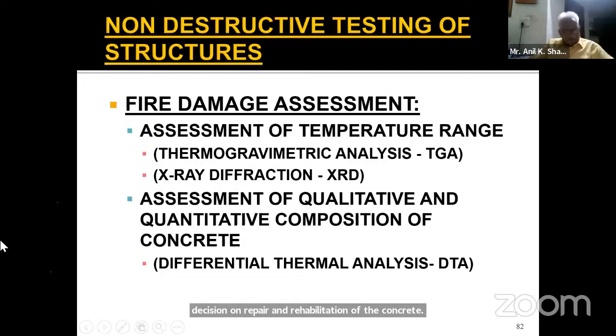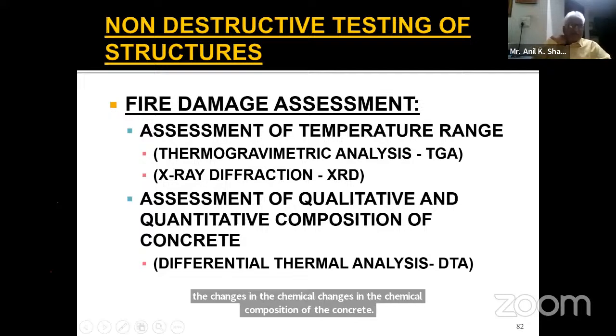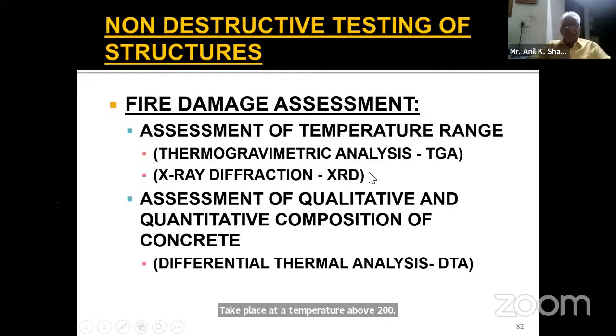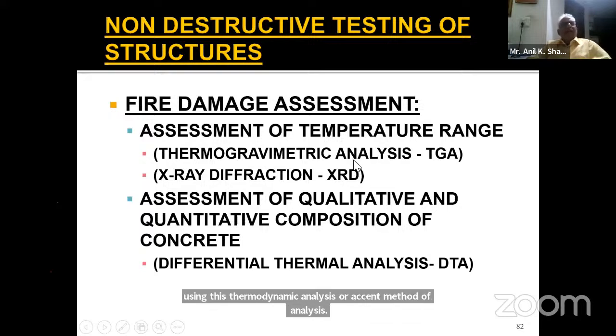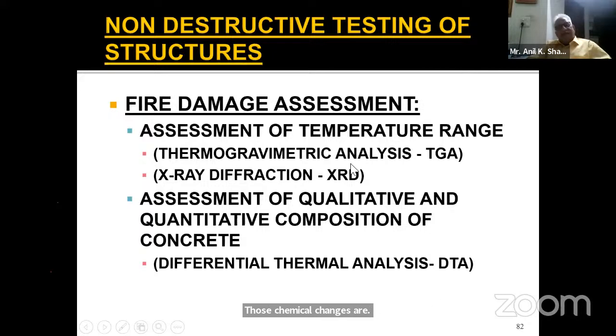Fire damage assessment is also needed when the structure has been subjected to fire. These are the special tests: thermogravimetric analysis, that is TGA, or X-ray diffraction. Here, the changes in the chemical composition of the concrete take place at a temperature above 200 degrees centigrade. Using this thermogravimetric analysis or X-ray diffraction method, those chemical changes are determined, and the temperature to which the concrete had actually been exposed is determined. Concrete starts losing strength at a temperature above 200 degrees centigrade. Up to 200 degrees centigrade, if the concrete is exposed, it is perfectly fine.